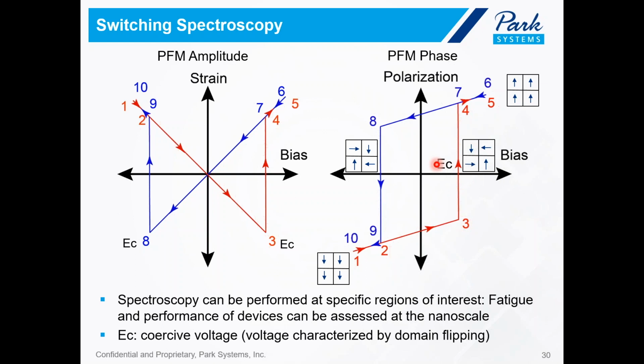The coercive voltage is a measure of the ability of a material to withstand an external electric field without depolarization. And the value can be determined from this PFM phase plot. So you can see in the schematic where we have random orientation of polarization directions before they take a predominant direction. So spectroscopy can really be performed at specific regions of interest, and from it we can learn about the fatigue and performance of the device at nanoscale.